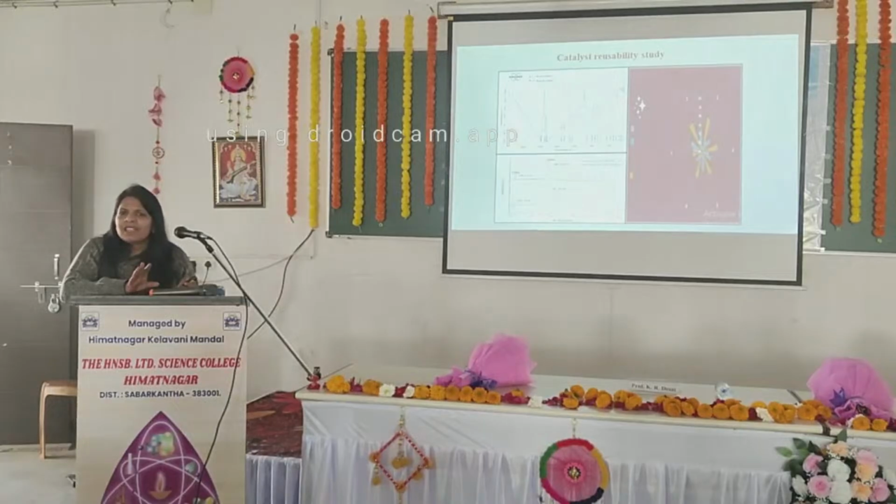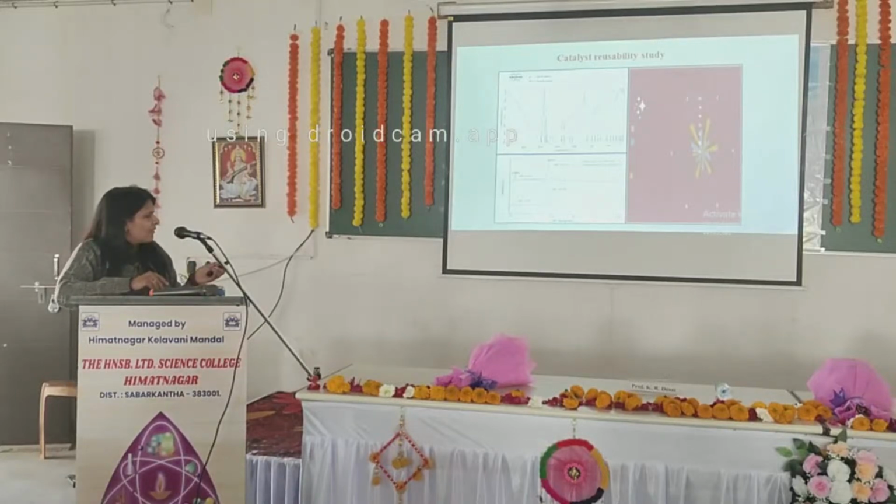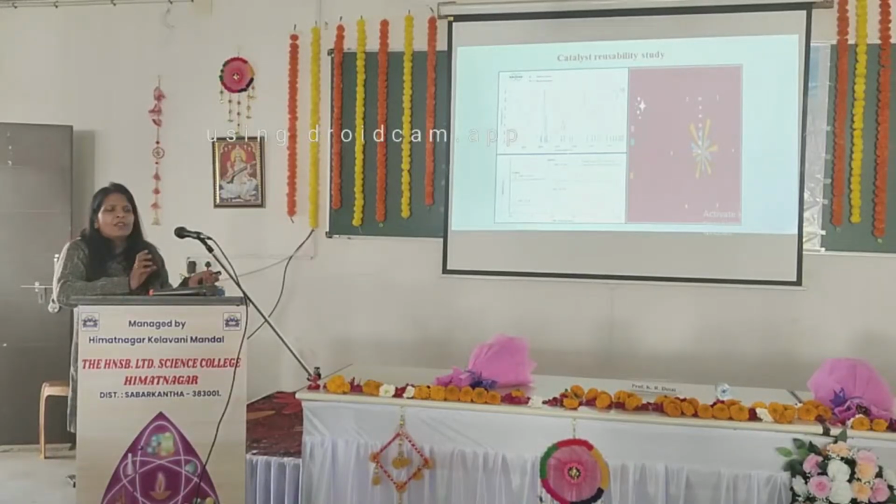Finally, for green chemistry, it is very necessary that the catalyst can be reusable after many cycles, because if it gets wasted in the first cycle, then it is of no use. So following the green chemistry principles, we carried out reusability studies, and it was found that the catalyst was active for 6 cycles with very little loss in catalytic activity, and the catalyst was confirmed by IR and XRD, and it was found that the catalyst structure has not been distorted and the sulfonic groups are present there.